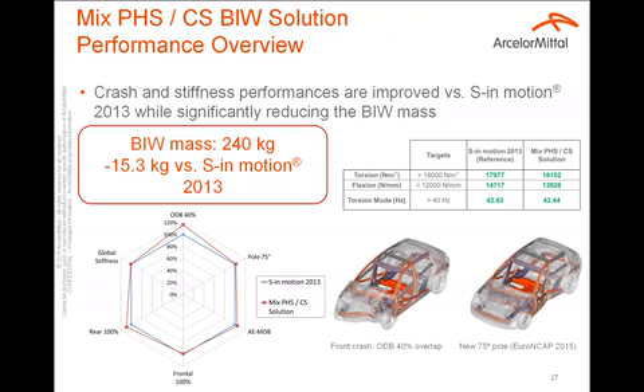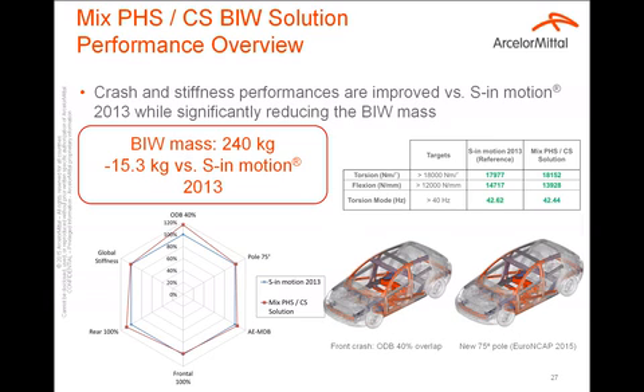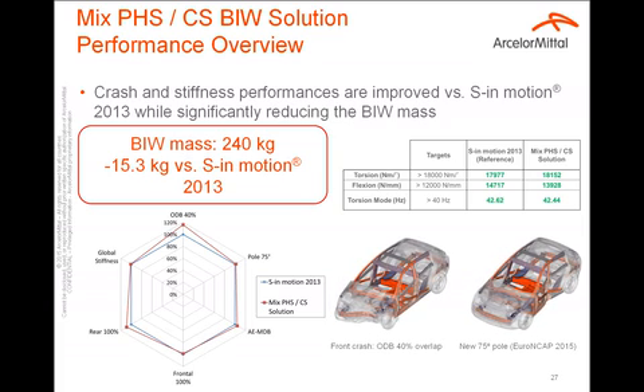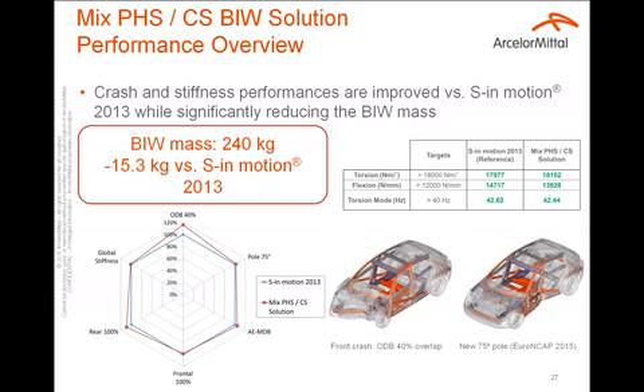This slide shows you the crash and stiffness performances obtained on that project, which are improved compared to our last S-in-motion solution with commercially available steel grades, while significantly reducing the body-in-white mass to 240 kilograms. So this new step allows us to offer 15 kilograms more weight saving potential in the new car structures. And when you look at the potential of alternative materials, it positions this kind of very light, full steel body-in-white very close to alternative body-in-white made of other materials, partially, of course.